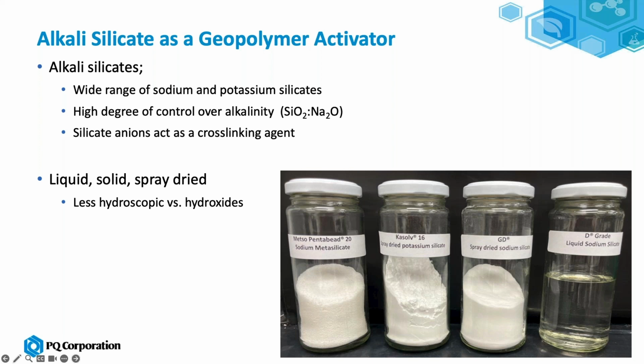One of the benefits of sodium silicate in powder form versus, let's say, caustic in a powder or flake or prill form is it's less prone to hygroscopic pickup of water. Some of the studies we've run looking at, and this is on the construction side, that geopolymers, even when they're well bagged, if they're alkali activated by caustic, they tend to pick up moisture over time and lose their reactivity. And this is much less dramatic using a spray-dried silicate or a metasilicate.